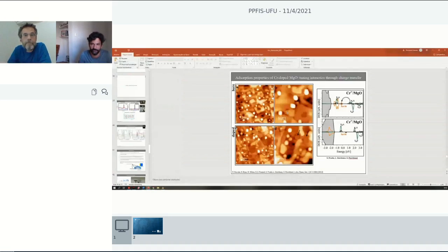Yeah, so these nanoparticles usually, this is not a nanoparticle. For instance, this example here, we are talking about nanoparticles in general, right? In this example, we have gold nanoparticles, and from their shape and size, I can judge what facet they are exposing. In this example we are depositing gold nanoparticles on bare MgO, and then on doped MgO, they can change their growth behavior and form this kind of 2D growth. That's why they look different here than this one.